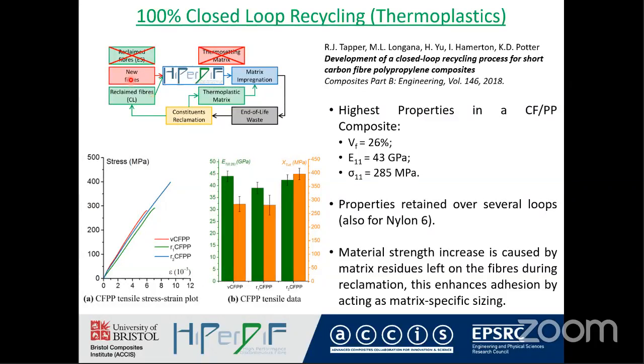So this is the combination of bringing new fibers into HyPerDiF, combining with thermoplastic matrix, looking at end of life, recovering constituents, taking out the reclaimed fibers, bringing them back into combination with a recycled thermoplastic matrix. And we've shown that for both carbon fiber and polypropylene, and carbon fiber and nylon 6, it's possible to retain the properties and indeed even improve the properties over several recycling loops.